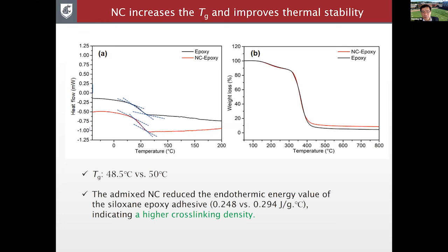And this phase transition also, from which we were able to calculate the thermal energy. So there's a difference between 0.248 to 0.294 joule per gram degree. So that indicates a higher cross-linking density, which agrees well with the previous literature, even though they were mostly using the epoxy for a coating, not for FRP adhesive.